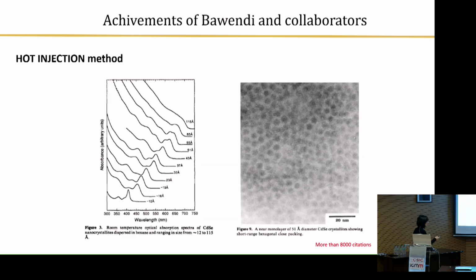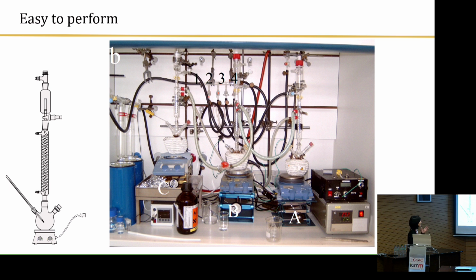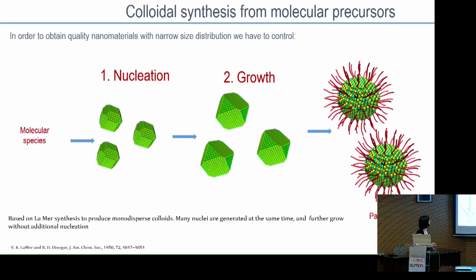So this is the original absorption spectra that they published in 1993, where you see this absorption edge shift depending on the size of the crystals, and a TEM image for that time. So this is something that you can do very easily on a small scale in the lab, as soon as you have a Schlenk line and a hood. Every inorganic or organic chemistry lab should be able to perform this kind of synthesis.